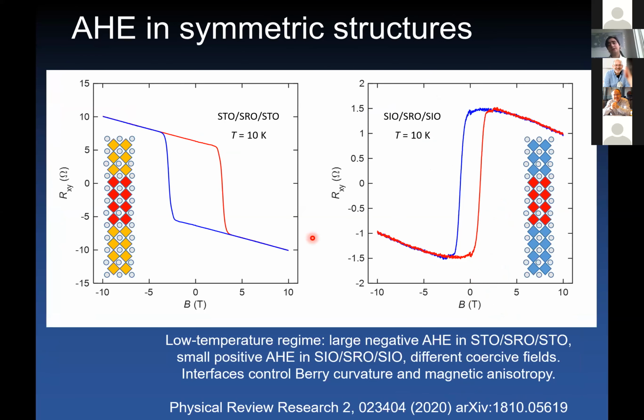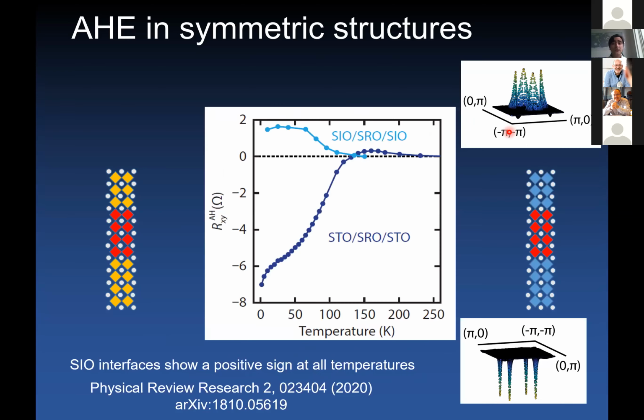And the bottom line is that the prediction of Cuoco and collaborators is actually verified in experiments. So if we measure films of strontium ruthenate, its anomalous Hall effect at low temperature, when it's sandwiched only by strontium titanate, you observe a negative sign of the anomalous Hall effect, a negative Berry curvature. Well, if you have a strontium ruthenate film of exactly the same thickness now embedded between strontium iridate, the sign of the anomalous Hall effect is positive. So you can indeed manipulate the Berry curvature.